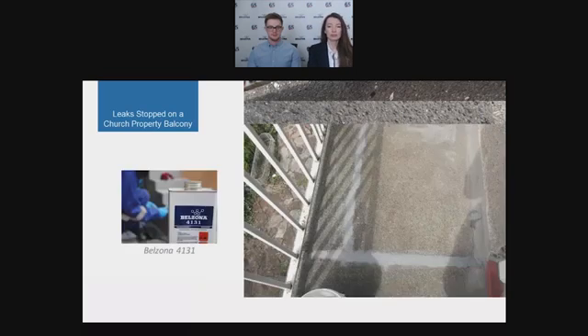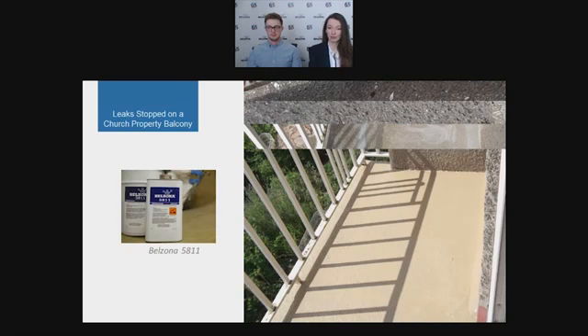The client wanted a solution which would be long-term and cost-effective, so turned to Belzona. For this application, the screed solution was specified, Belzona 4131. This was because of its outstanding adhesion and ability to feather edge, so this was used to repair the cracks. And then to fully waterproof the balcony, Belzona 5811 was coated on top. This also left an aesthetically pleasing finish on the balcony.